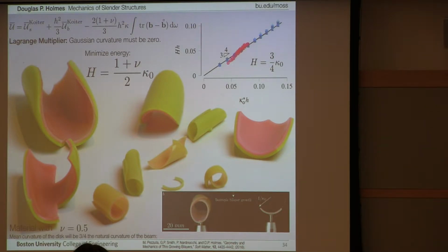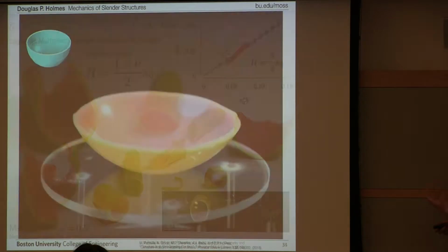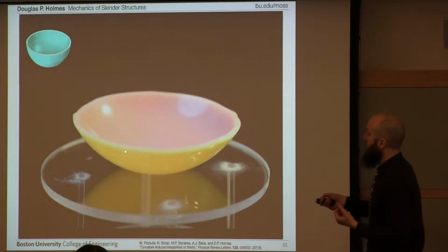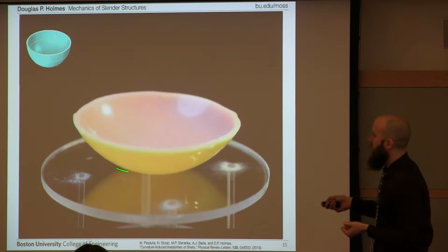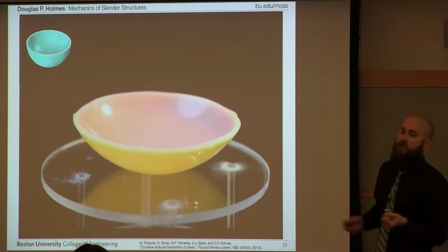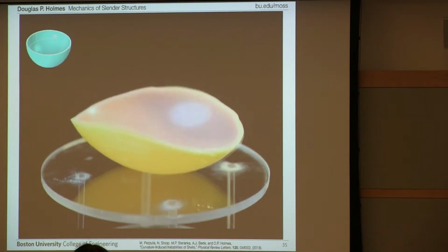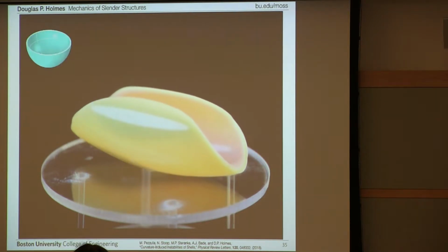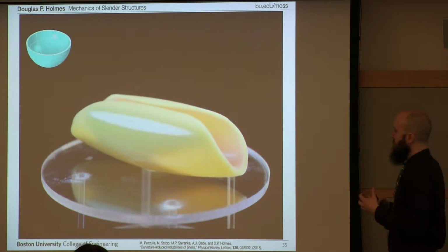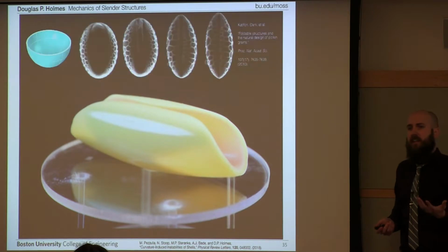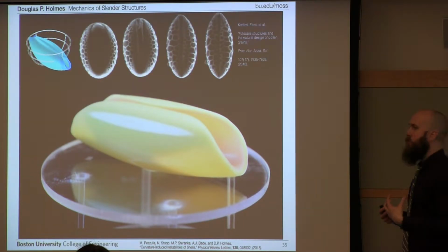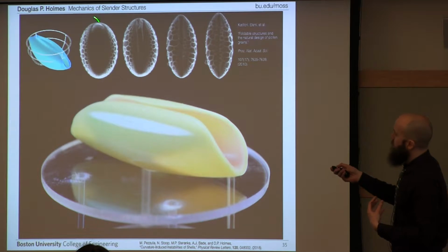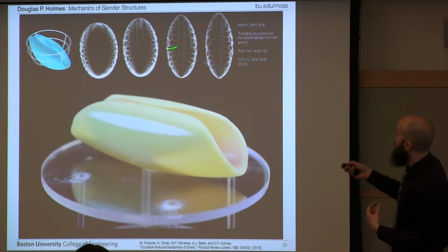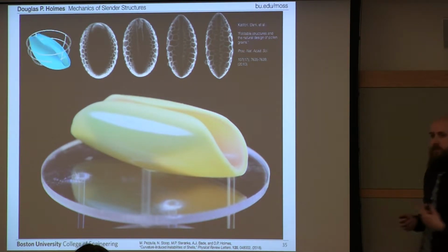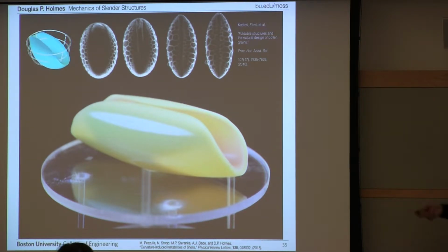So once we understood this, we moved on to more complex structures like a shell. So here's a bilayer shell where the outside of this layer wants to get bigger, the inside of this layer wants to shrink. We let residual swelling impart a natural curvature stimulus on it, and we watch how it deforms. And this looks kind of familiar, right? This kind of looks like that pollen grain folding that we saw before, in which you had a spherical shell that was subjected to a natural curvature that kind of wrapped up into this spindle-like shape here. In fact, to go from this spherical shell to this shape here, this thing buckles.